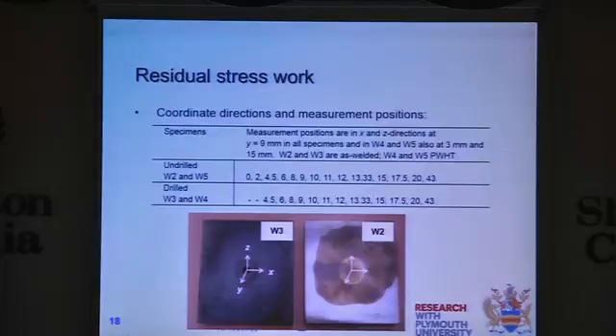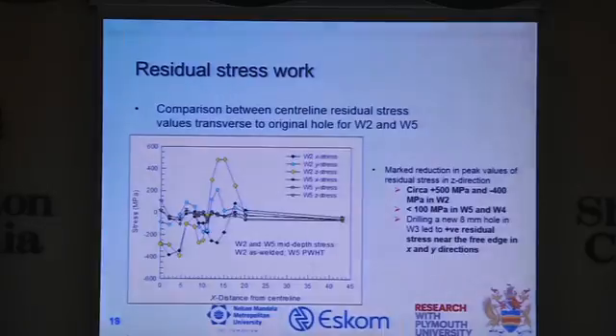That's the matrix we've used to measure. I'm not going to go through that. It's just three levels of stresses that you quantify. But in this graph, what I'm showing you is two sets of welds, the W2 sample and the W5 sample. The W2 sample was as welded, and the W5 sample was as welded with post-weld heat treatment.